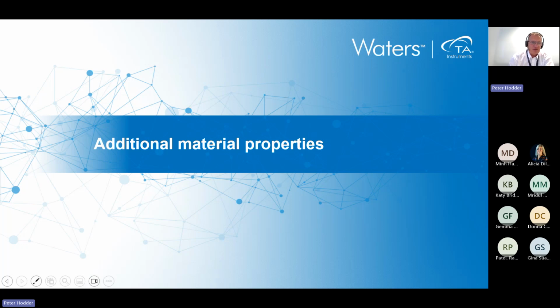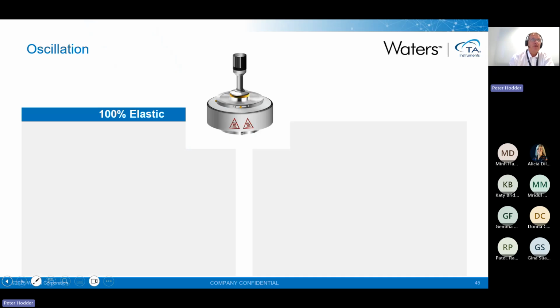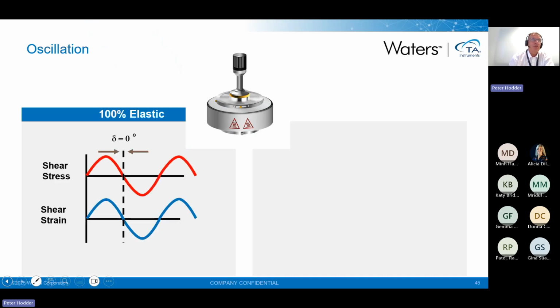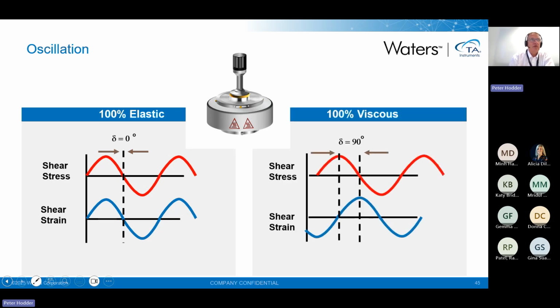So what I want to do now is just remind you that the rheometer is on the higher end of the scale performance-wise, and that's because it can do oscillation testing. That means we can look at whether a sample is elastic. So when we do an oscillation, we actually operate the geometry backwards and forwards. We wobble it. And we can see that if it's purely elastic, the sample follows the geometry. If it's purely liquid, it lags behind and we have a thing called a phase angle between 0 and 90.